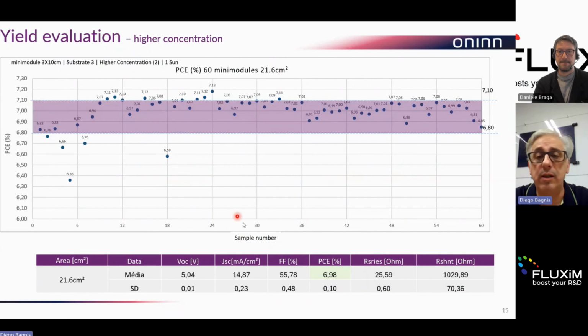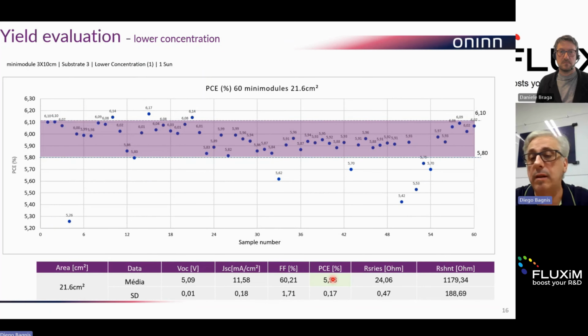As I said before, the yield is one of the main parameters, so just to show a couple of graphs about that. Here we're speaking about the best condition, with substrate 3, with the higher concentration, at one sun. We're speaking about 60 minimodules coated on the web and measured, and we arrive close to 7% on average, with the standard deviation that I mentioned before being really, really small. If we take the same parameters but reduce the concentration, you can see that we lose more or less 1% absolute in value.